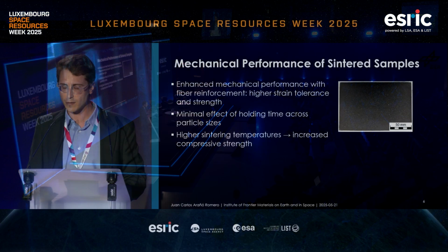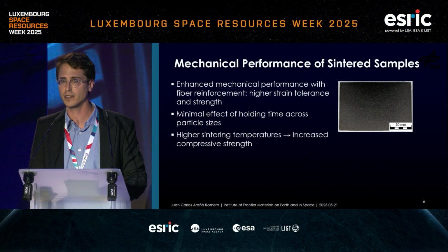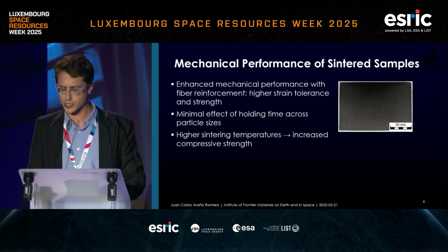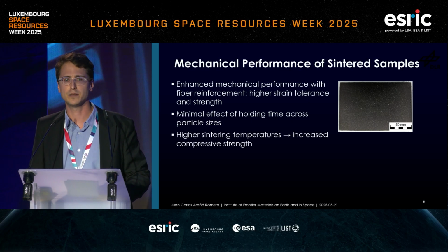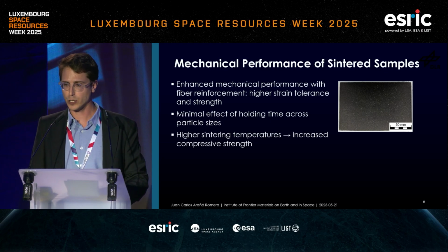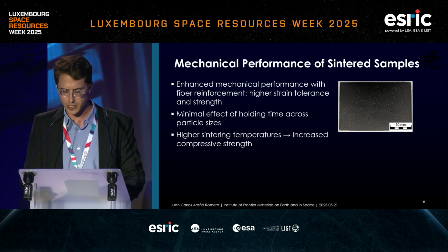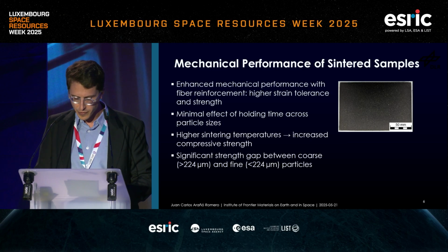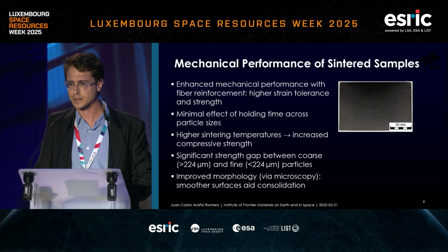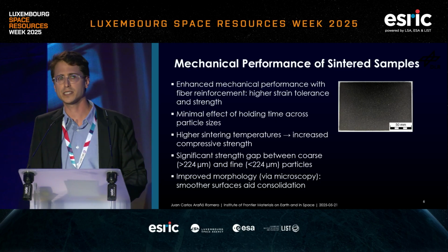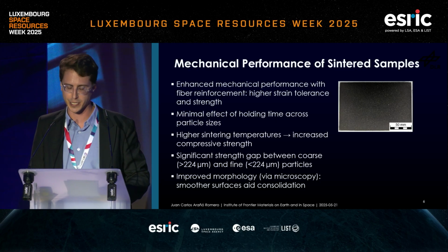But higher sintering temperature clearly led to an improvement of the compressive strength, which could be due to the higher liquid phase. There was also a significant strength gap depending on the particle size. Logically, as could be expected, finer particles gave better results because there was a higher surface area, and then the particles could bond better. We also examined the raw material under the microscope, and we saw that it actually has a smoother surface than real regolith, and that actually helps the densification of the sample during sintering.